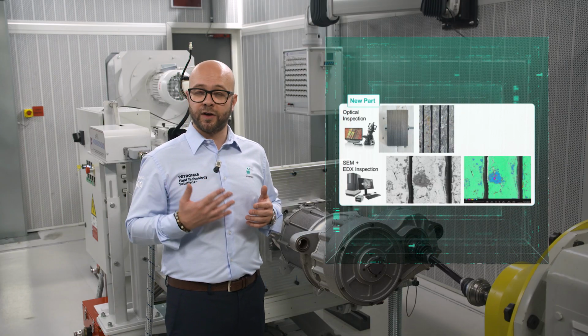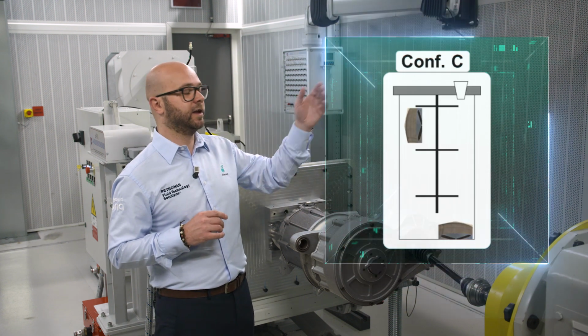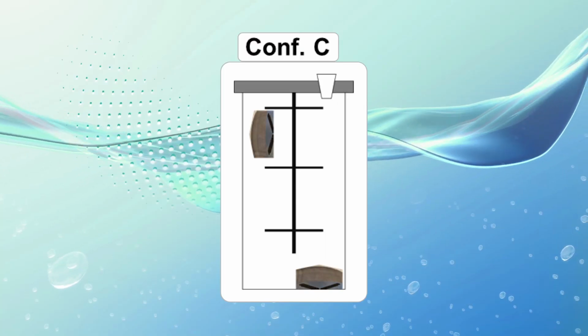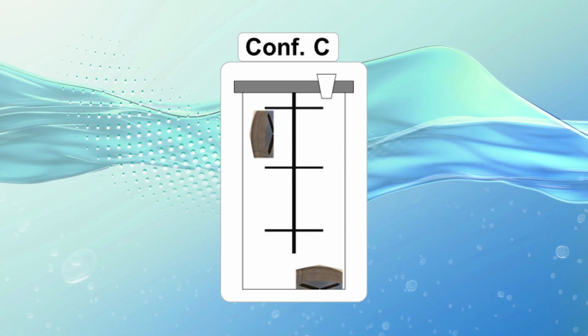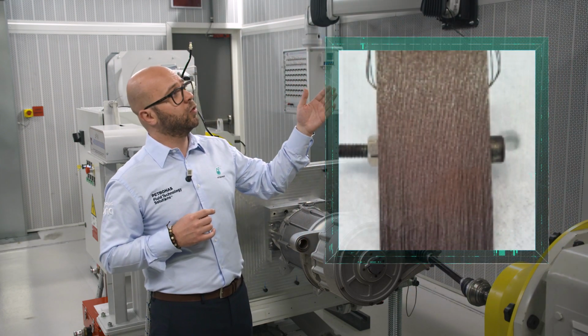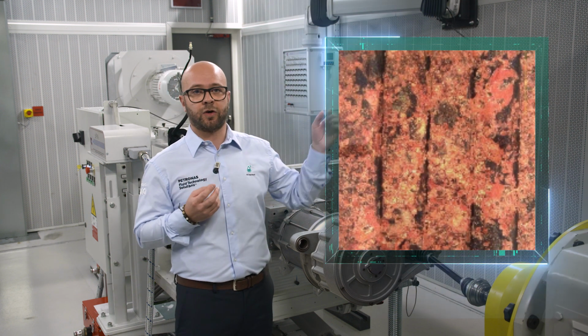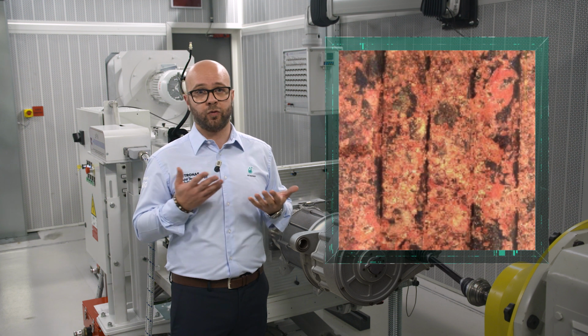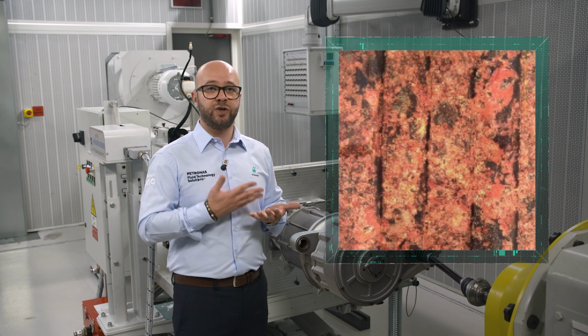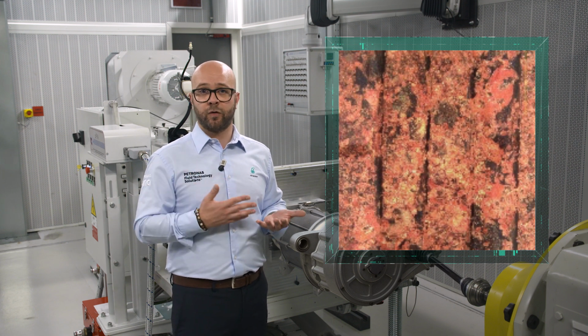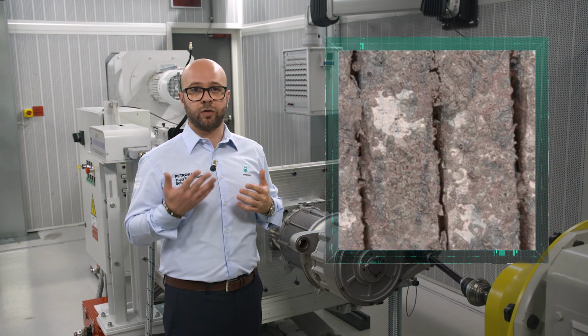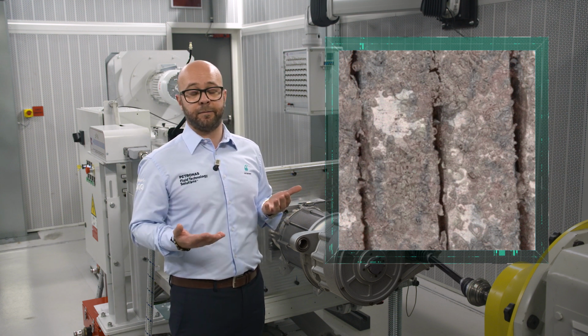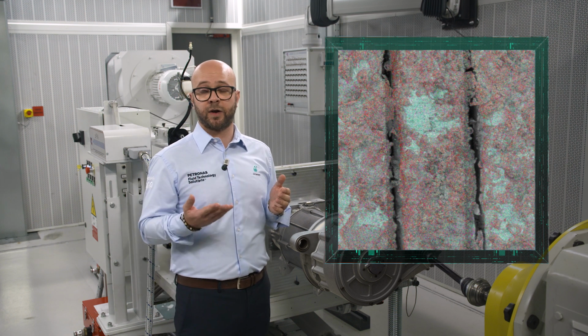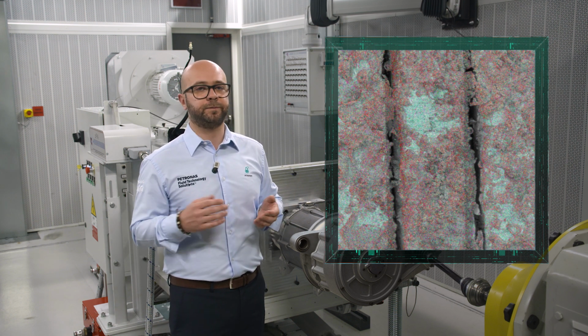The test is still ongoing, but today we are able to show you the results regarding configurations A and C. Let's start from configuration C, where we assess the corrosivity due only to the humidity in the environment of the test. The surface looks damaged with a reddish color. This color is clearly associated with a layer of iron oxide formed on the surface due to the condensation of water on the surface of the part. This is also confirmed by the SEM image that shows a contrast in the backscattered image, and also in the EDX analysis we observe the presence of iron and oxygen on the surface.